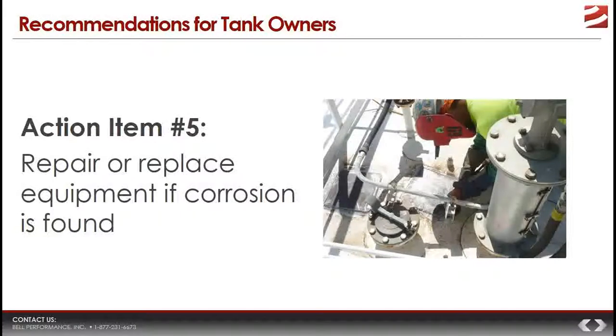How quickly is as quickly as possible? Another way to put it is, how quickly can corrosive damage from, let's say, MIC happen? Well, the literature values for corrosion in diesel tanks is 0.3 to 0.5 millimeters per year. Now, by literature values, what we mean is that you don't have micro problems, you have clean fuel, you don't have the presence of any accelerating factors. It's just, things are pretty good in that tank. You can still get up to 0.5 millimeter per year of corrosion.